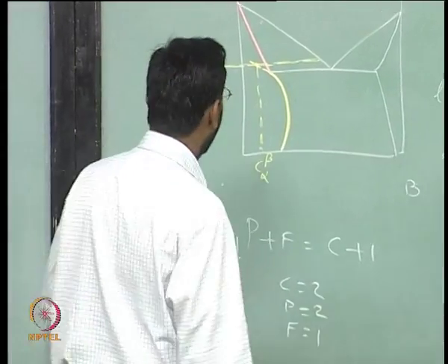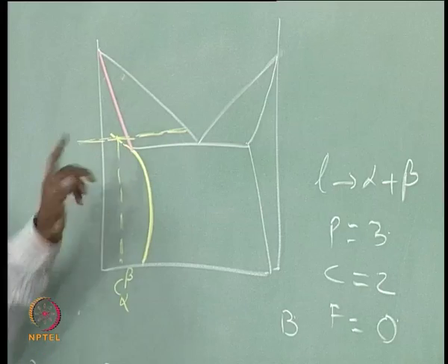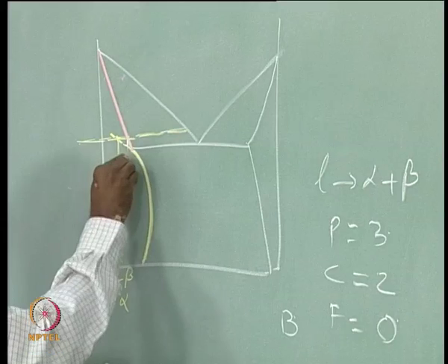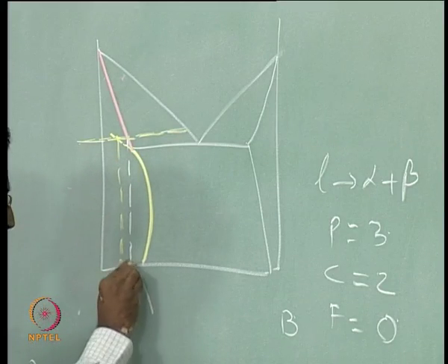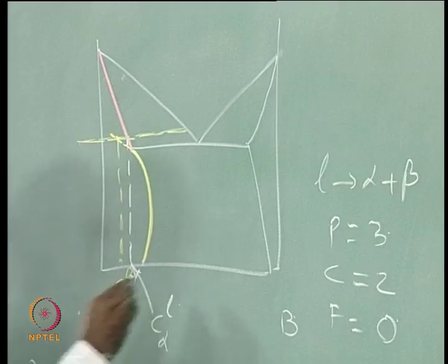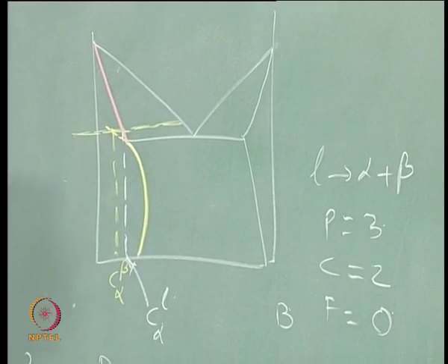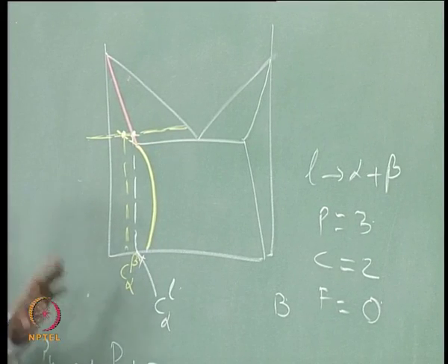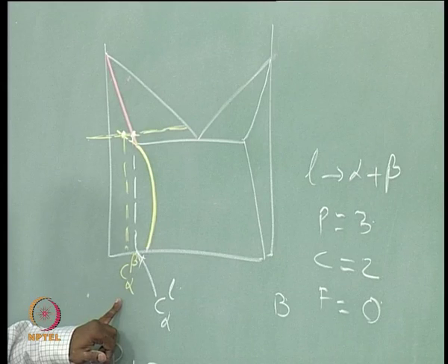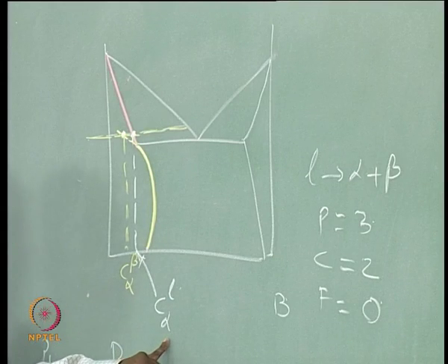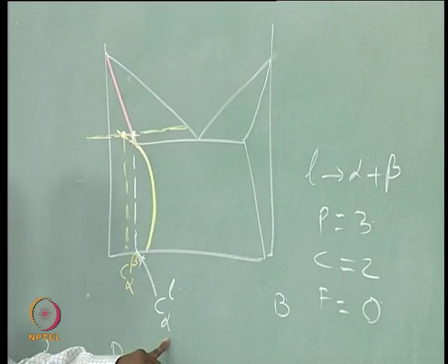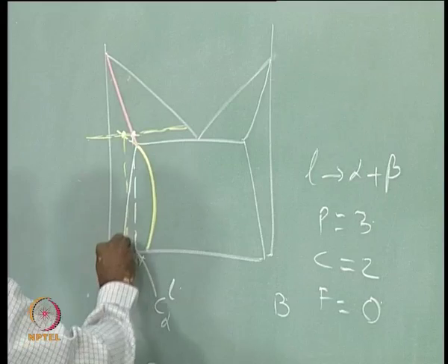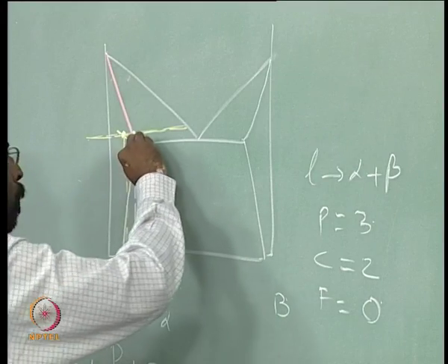So, now if that is the case, this composition, what does this tell you? If I extrapolate this composition, it is telling that C alpha beta is for me, this is C alpha liquid at that temperature. At that temperature, this is the C alpha liquid, this is the C alpha beta. So, this tells you that C alpha beta is lower than C alpha liquid in terms of solute, which is wrong. Whereas, if I draw the solvus line like this and if I extrapolate the solvus line,